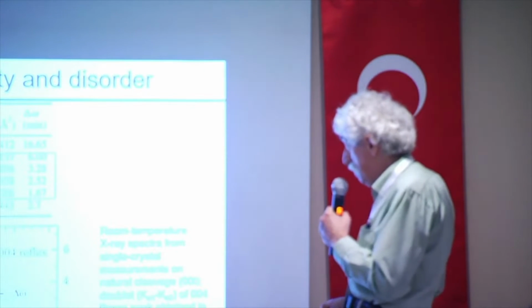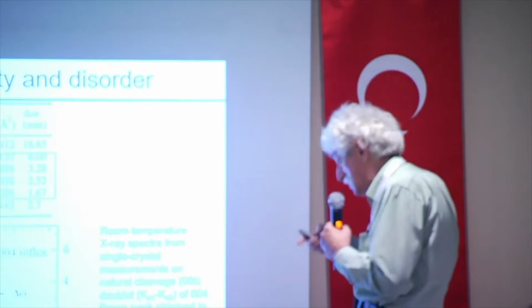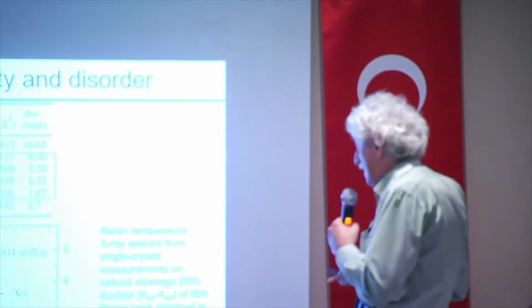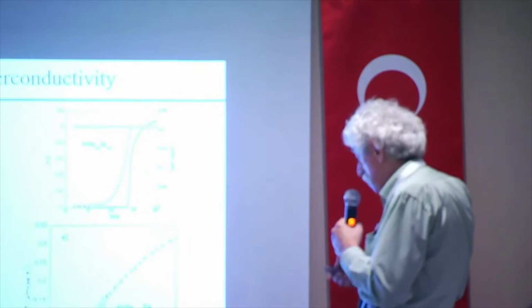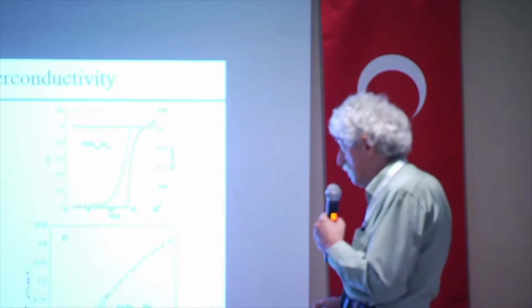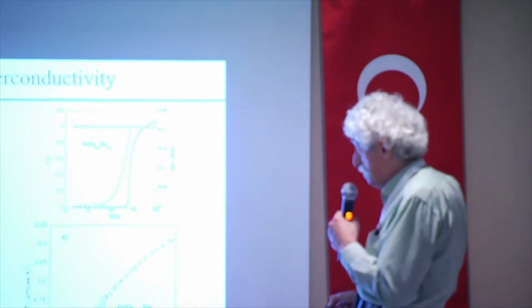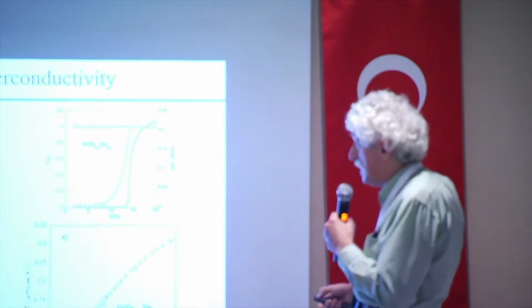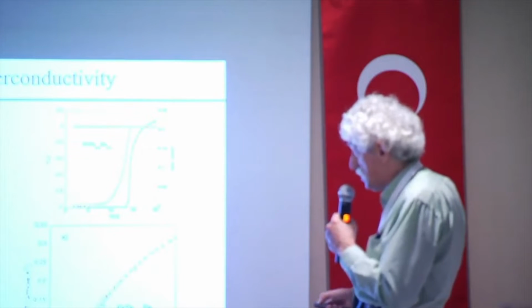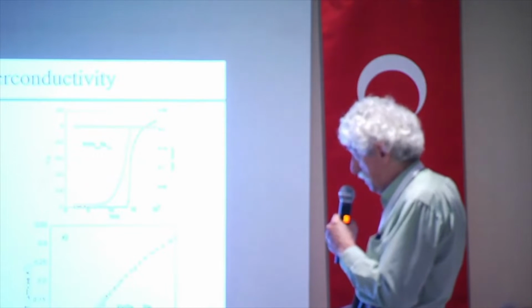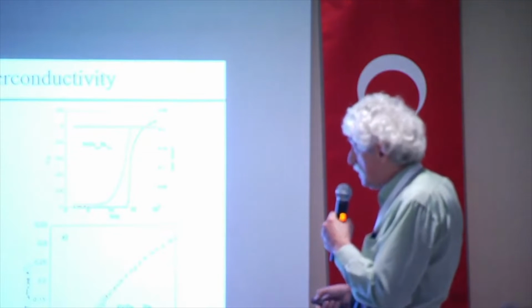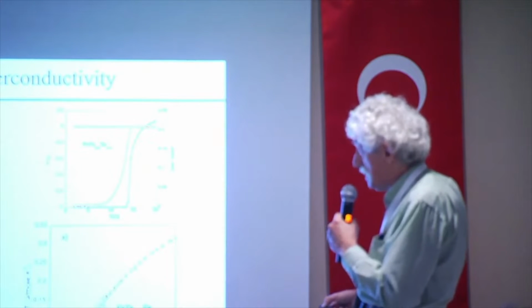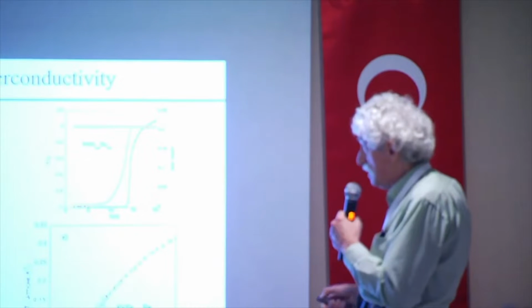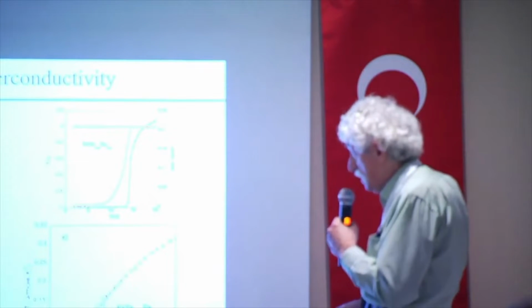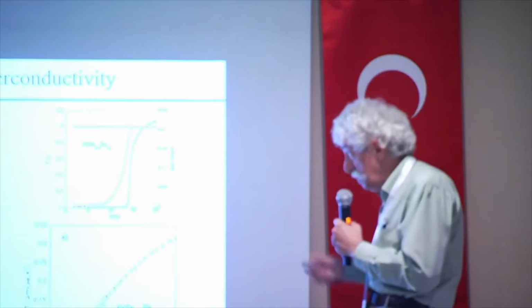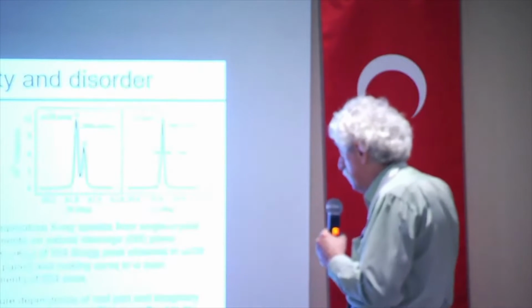the 0.04 peak. And if you compare the superconducting state properties of these crystals, you can find a huge difference, although the nominal composition of the crystals is identical. You can see here a very sharp transition and a very well developed heat capacity peak. But in another crystal, which was grown in slightly different conditions, the superconducting transition is very wide, and the peak in heat capacity is almost not developed.